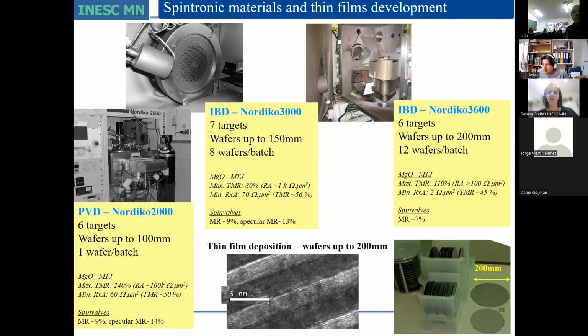If you look at this, for AMR you just need 2 targets, you don't need more. For GMR, we may need 6 targets, 7 maximum. But if you look at TMR, the structures are so complex now that we easily end up needing 9 targets, 10 targets, with the buffers and cap layers and heavy metal in the middle, so tungsten there and so on. So it's very important to have more targets in the same vacuum tool.